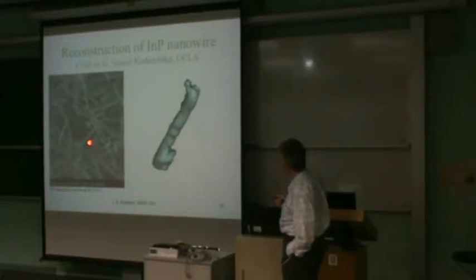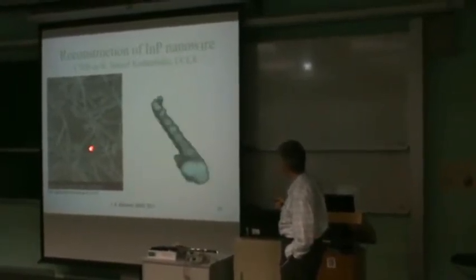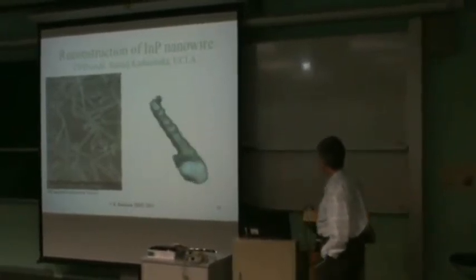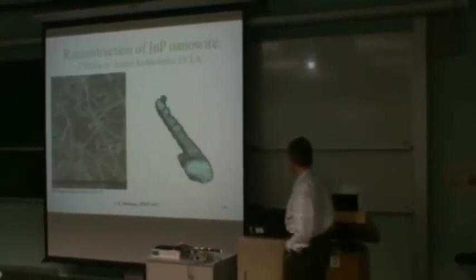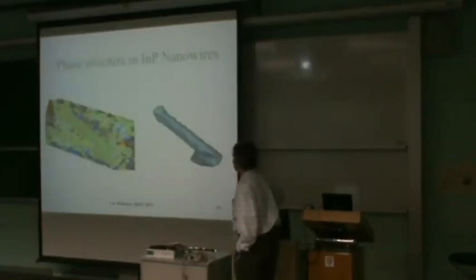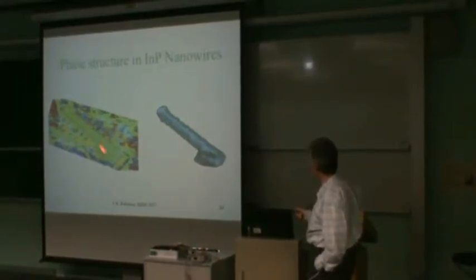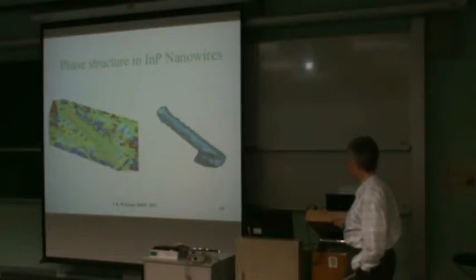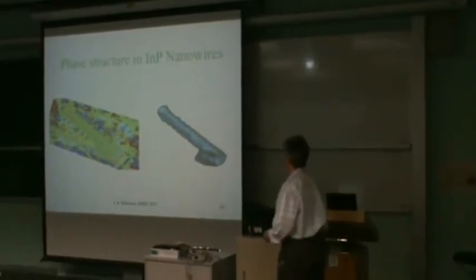And the thing that was interesting here, because they do grow from a catalyst, and there is a sort of residual root that occurs on these samples, which is this end of the stick here. We were interested in whether there is a strain difference between the wire part and the root part, and the answer is a very slight one. So there's a very slight color gradient along the wire here, and no color gradient, just a single color here. Possibly the center of the crystal has a little bit different strain from the edges, but anyway, it's not a particularly dramatic effect that we're seeing.